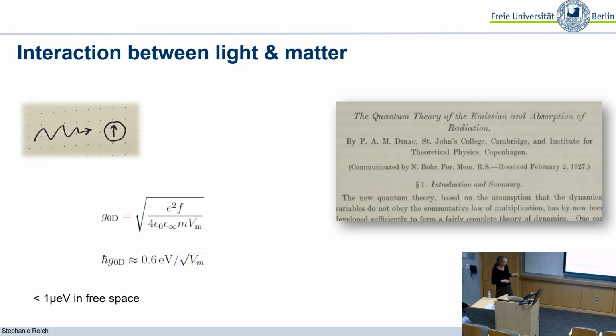for an oscillating electron, you will find that light-matter interaction is 0.6 eV per the square root of the mode volume. And if you describe the mode volume as a photon flying through space, with a certain interaction cross-section and a certain kind of lifetime for the entire pulse, you will find that light-matter interaction in free space is less than 10 to the minus 6 eV. So compared to the transitions that you're looking at that are on the order of eV, that's really a very tiny quantity, and you can safely introduce this as a perturbation.